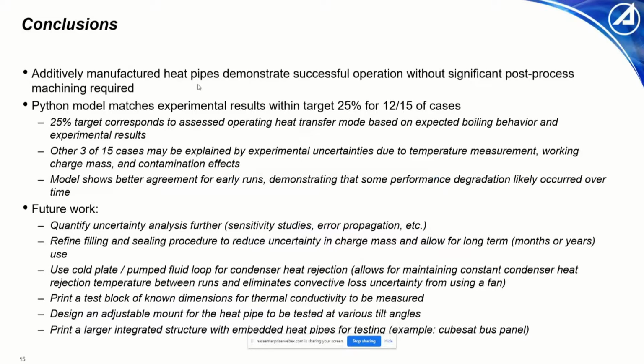Additionally, the Python model matches the experimental results within the target of 25% for 12 of the 15 cases. The 25% target corresponds to the assessed operating heat transfer mode based on both expected boiling behavior and trends in the experimental results.